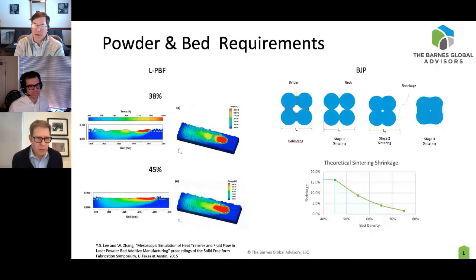If we're talking about more press and sinter with pure metals, not the traditional PM materials, I think the same case happens, right? A lot of times, die filling and compaction has an influence on the distribution of porosity in a very different way than layer upon layer injection of powder and binder.